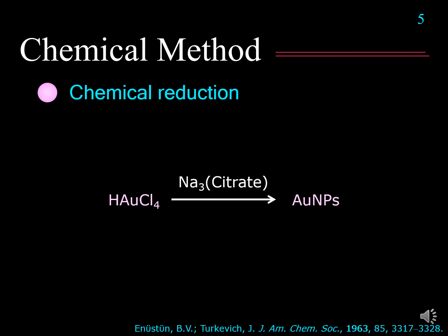But sodium citrate is very popular here because sodium citrate is not really reactive, so it's quite stable and controllable compared with sodium borohydride or something stronger than that, which is very difficult to handle, very difficult to control. So sodium citrate is a very good choice, and we normally use it for the gold nanoparticles.